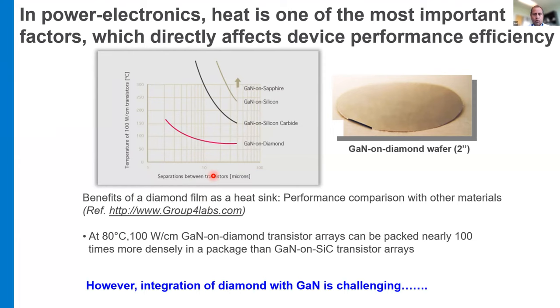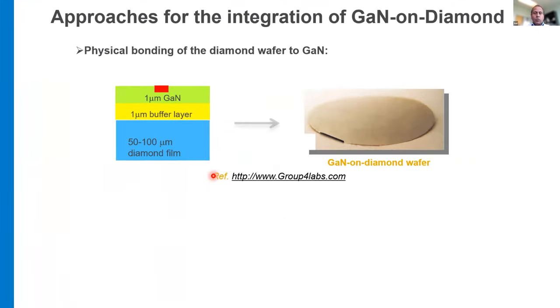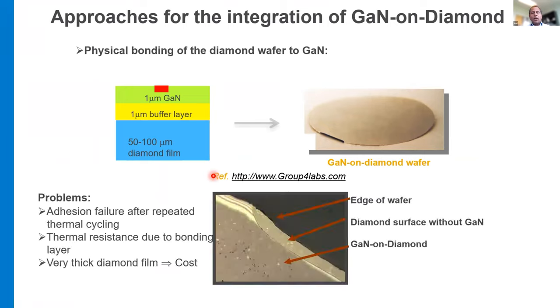I think one important fact that I want to mention is that this is also a product now available from various diamond companies. But this is one of the approaches which has been used for physically bonding diamond directly to gallium nitride through some kind of buffer layer. It could be silicon nitride or silicon oxide. But one of the problems that you see after repeated thermal cycling is the bonding layer and the adhesion of the bonding layer, as you can see, comes off because of the thermal expansion coefficient mismatch.